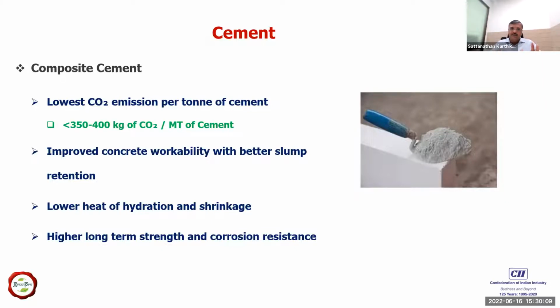There is another cement available, composite cement, which is gaining a lot of importance nowadays, wherein both fly ash as well as GGBS are used for making the cement. The carbon footprint of this cement is even lower. The workability is much better compared to the other cements, with lower heat of hydration and shrinkage, and very good corrosion-resistant properties. Obviously, it reduces the embodied carbon of the whole building. Friends, it is not only about reducing embodied carbon. When you go for these blended cements, you will also be able to reduce the cost of construction. Compared to ordinary Portland cement, these products have a lower price because of the increased additives. You can have a cost comparison at the market as well.